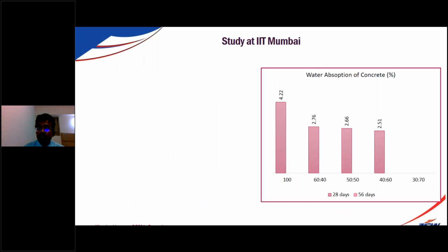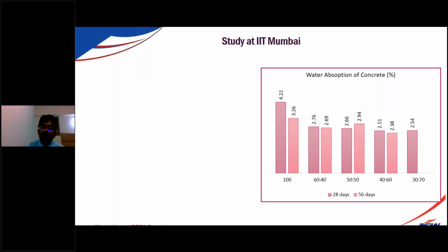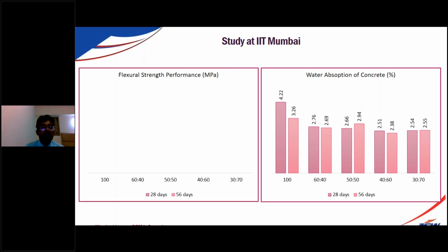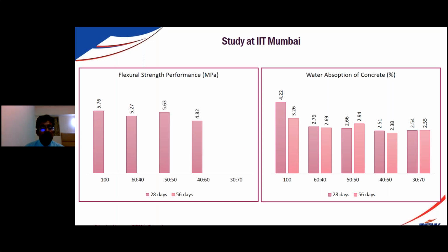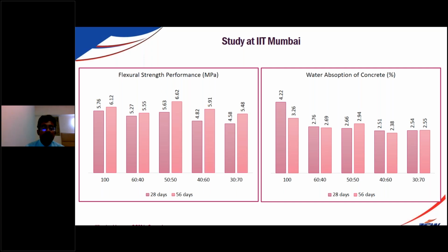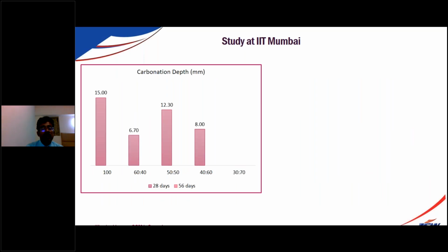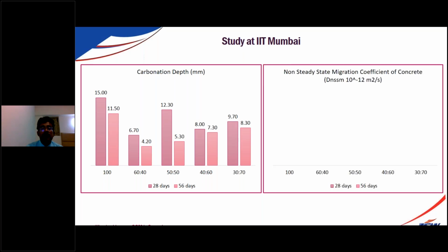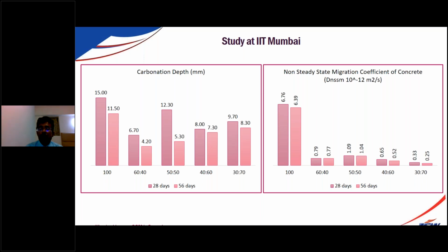Looking at the water absorption, you can see the results at 56 days, the higher replacement is coming down gradually. Similarly, flexural strength we have also seen at 28 days and 56 days, giving better performance with higher replacement. We have seen optimum results at 50 to 60%. Similarly, carbonation depth gets reduced with higher replacement levels compared to the OPC mixes. Migration tests, I'm going to share the PPT with all of you.